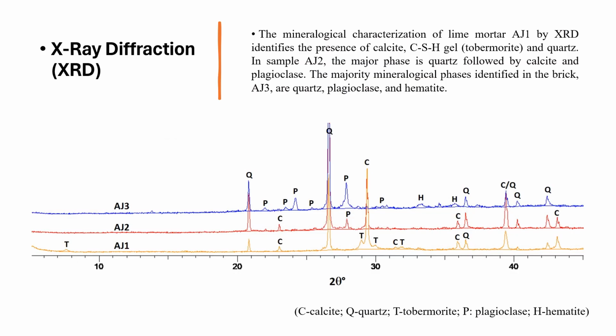The mineralogical characterization of lime mortar AJ1 by XRD identifies the presence of calcite, CSH gel, tobermorite, and quartz. In sample AJ2, the major phase is quartz followed by calcite and plagioclase. The majority mineralogical phases identified in the brick AJ3 are quartz, plagioclase, and hematite.